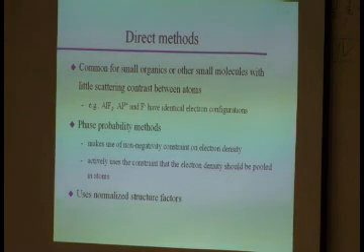So your Patterson map would look rather confusing, because yes, you have the Al-Al distances, which come from equivalent positions. You have the F-F distances that come from equivalent positions, but all your Al-F distances that have nothing to do with your interatomic distances from symmetry equivalent atoms will also show up at about the same strength. Well, that sucks, to put it very non-scientific, okay?